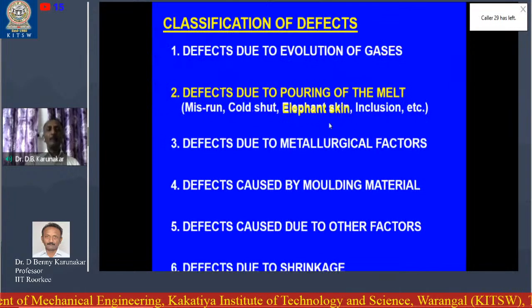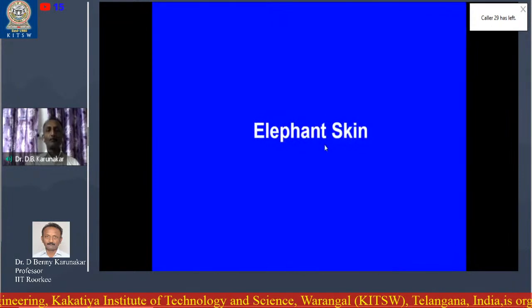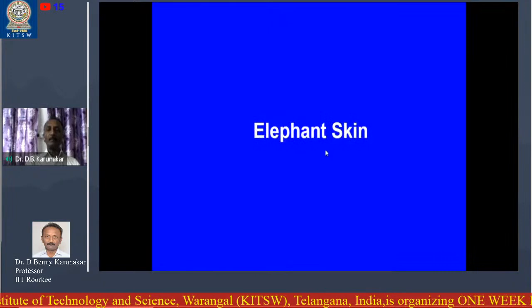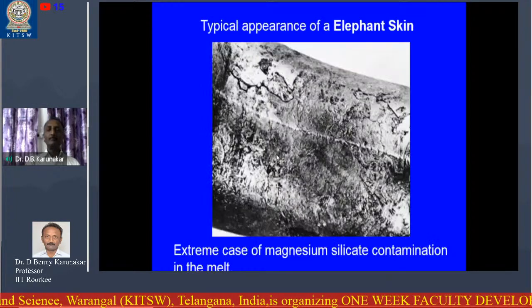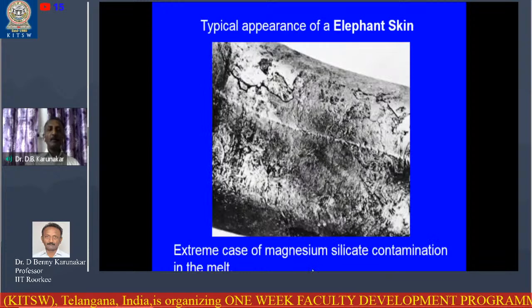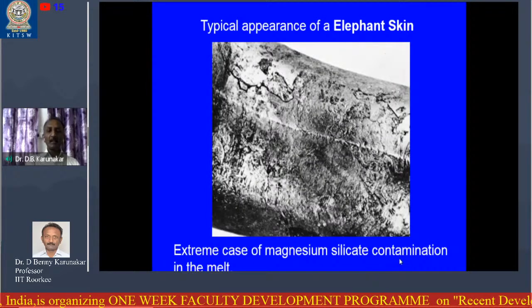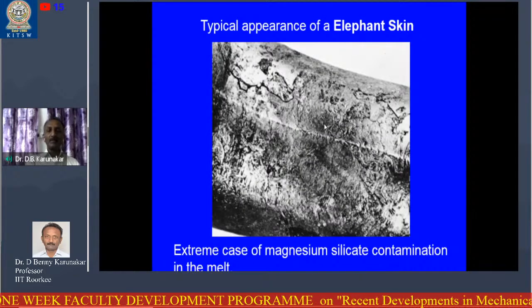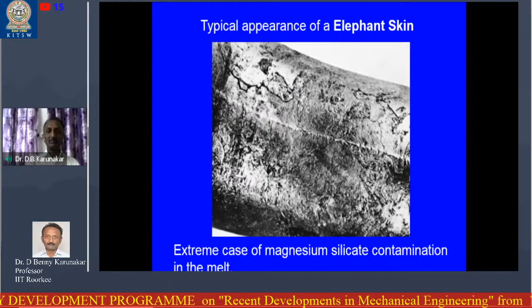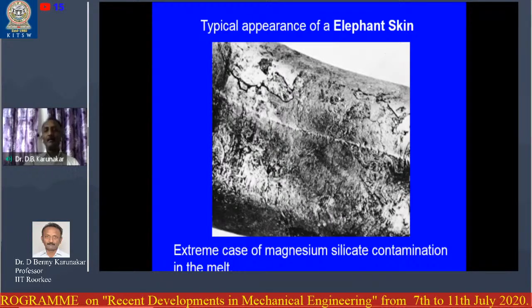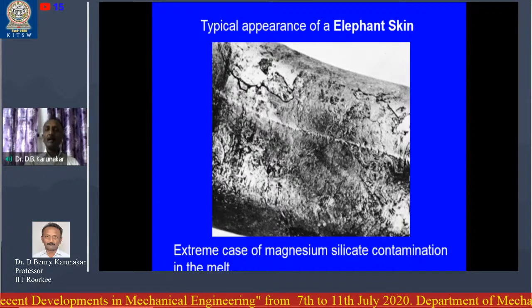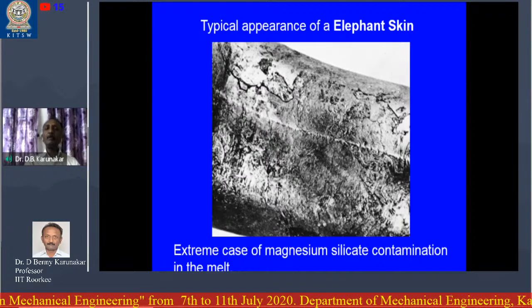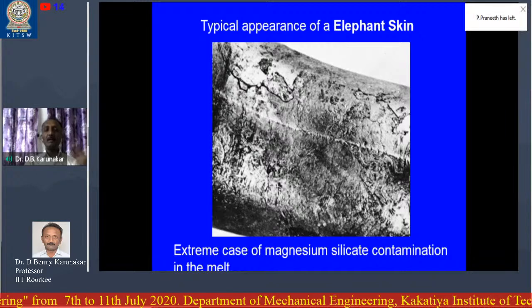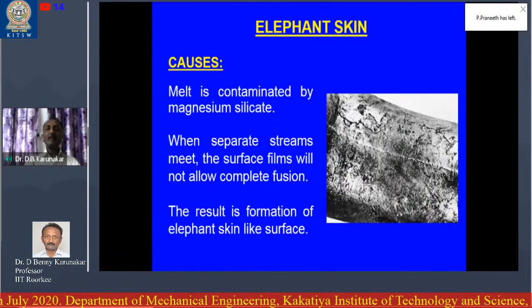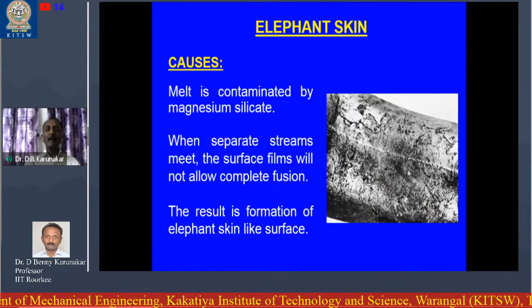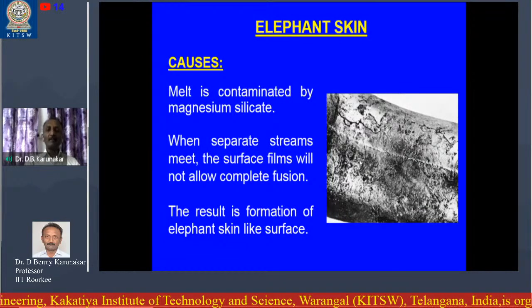Next one, elephant skin. What is this elephant skin? If it looks like this, it's an extreme case of magnesium silicate contamination in the melt - you see it looks like this. It's a rare defect, rarely spoken about, rarely feared. The melt is contaminated by the magnesium silicate and it is deposited on the casting surface like this.